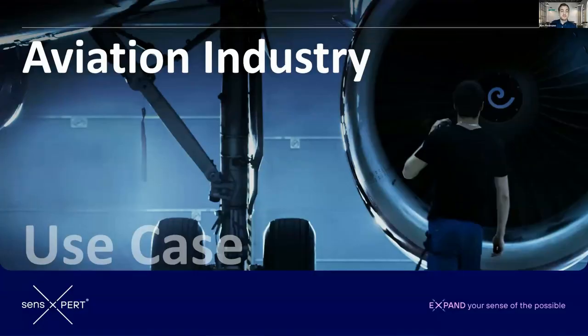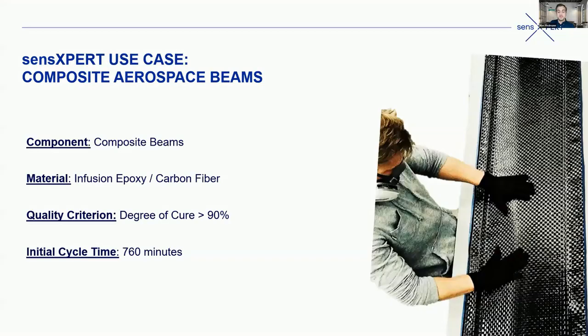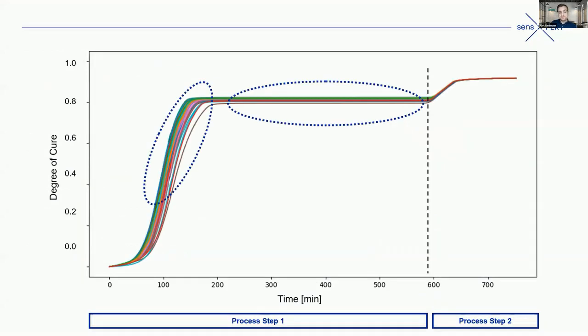And so if we look at this as a quick case study in the aviation industry, we have customers manufacturing really large composite beams, again with an infusion process, but using carbon fiber, and their only real target was a degree of cure greater than 90% before they could demold. And so they had a really long initial cycle time of 760 minutes. And we just installed one of the sensors into the mold and looked at what we could see. And this is like the first 50 parts or so, and we're measuring here the degree of cure.